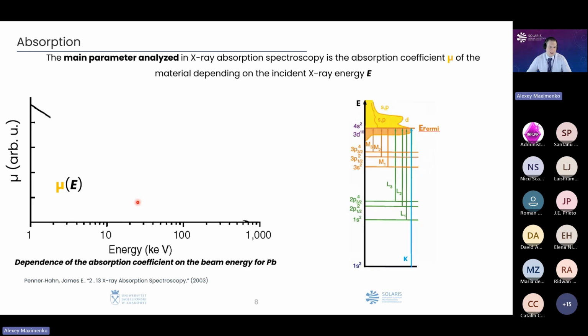Let's discuss what we actually analyze when we perform X-ray absorption spectroscopy measurements. We analyze how the absorption coefficient changes depending on the energy of the photons with which we irradiate our sample. For example, let's have here a function of this absorption coefficient, and we change the energy of photons. At first, with increasing photon energy, the absorption coefficient will decrease, taking into account that the probability of interaction of these photons with the atom will be lower.